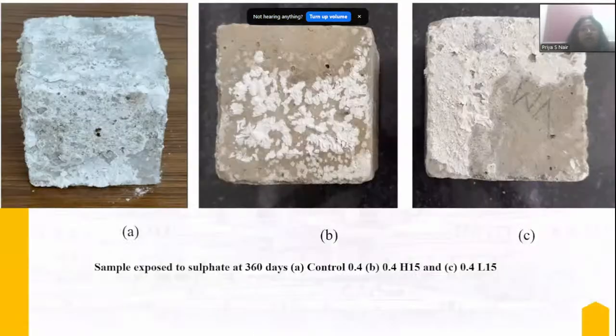These are the images of the control as well as the sulfate higher and lower consortium samples. I extended my work up to 360 days, and I noticed that the higher and lower consortium samples do not show any visible changes and were not degraded. Maybe something happened inside, but nothing was visibly shown, like cracks, demolition or spalling.